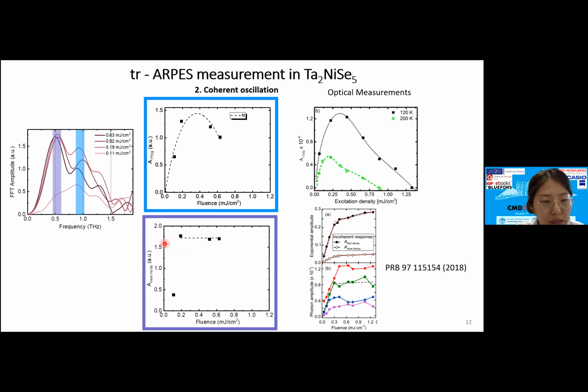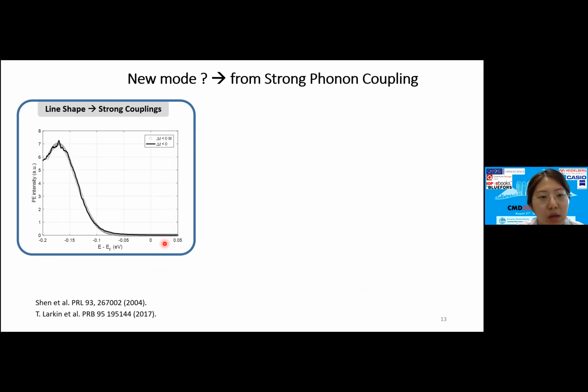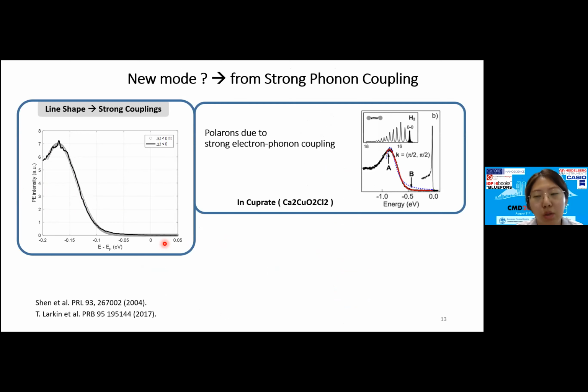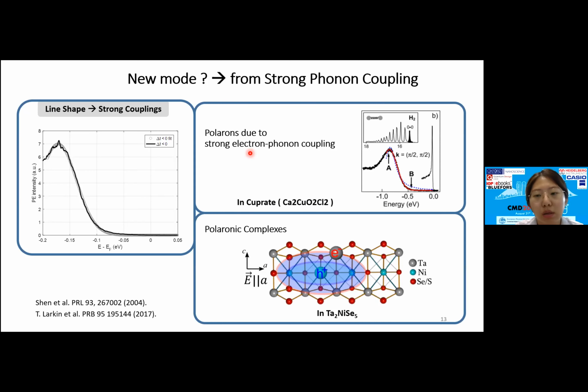But we know already from the line shape of our band that we can assume there is a strong coupling to the phonon, because when we compare to the cuprates, it shows an anomalously broad band, because they suggest there is a polaron in the system with strong electron-phonon coupling. As already suggested in the static optical measurement, we suspect there are polaronic complexes, and this polaronic mode is from these polaronic complexes.